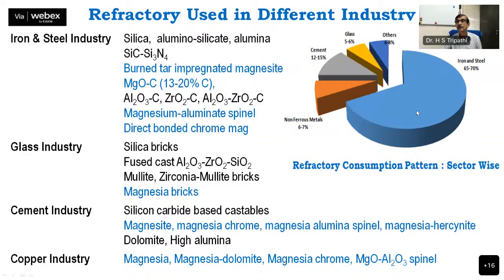And if you see the percentage of refractory used in iron and steel, it is about 65% to 70%. Then the cement, then non-ferrous, and some glass and other industries. In glass industries the magnesite brick is used. In the cement industry, magnesite, magnesia chrome, magnesium aluminate spinel, and different types of magnesia are used. And the copper industry also uses magnesia dolomite, magnesia chrome, and magnesium aluminate spinel.